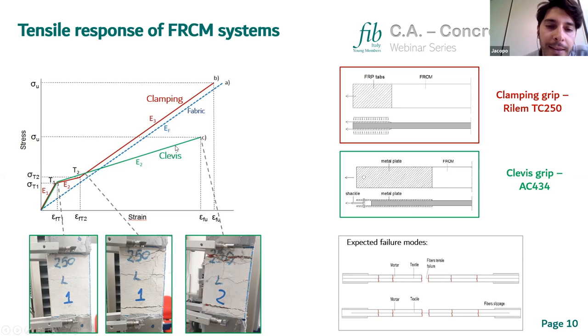And then we have the fabric is also involved, and the slope of the second part of the curve is mainly due to the adhesion that develops between the fabric and the mortar. In the case of clamping, we have the same behavior in the first part where the mortar is still uncracked. Then we have the formation of cracks with the lower elastic modulus. And then the curve, let's say, is like if we are testing only the internal bare reinforcement. So the slope of the curve is very similar to the slope of the fabric within the mortar.